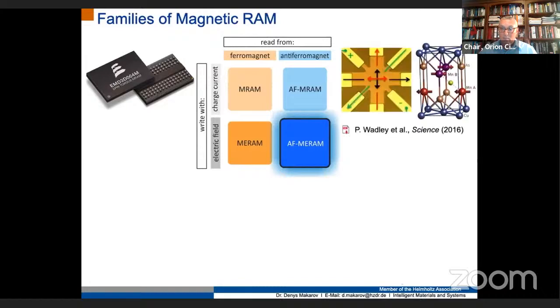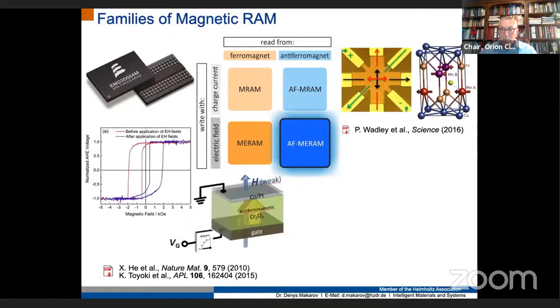There is an antiferromagnetic counterpart of MRAM where you use charge current to write information in, for example, metallic antiferromagnet and read out the information from metallic antiferromagnet. Our work is inspired by the activities of the group of Christian Binek on the realization of magnetoelectric random access memory, where the magnetoelectric insulating antiferromagnet chromium oxide is interfaced with ferromagnet, and the magnetic state of the ferromagnet can be manipulated by the electric field which is applied across the antiferromagnetic insulating material.